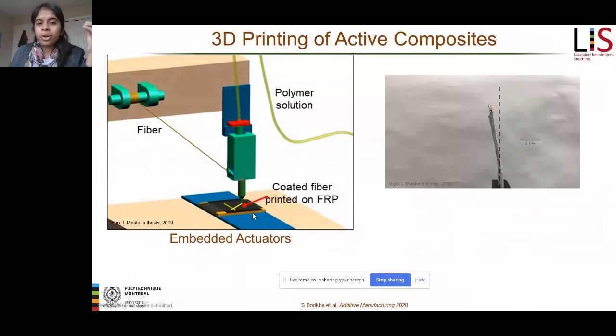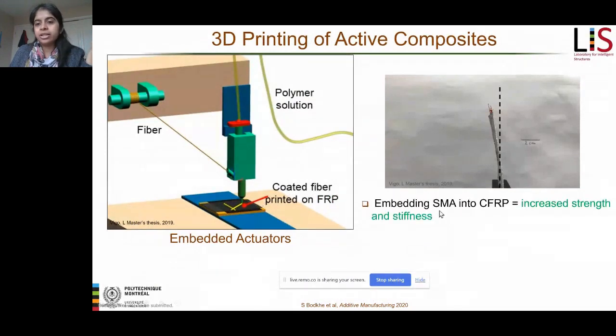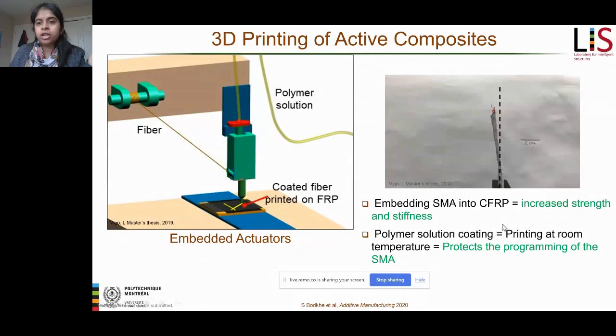So what we did was we tried to print these SMAs into composite prepregs. And then we cured these prepregs and we ended up getting really strong structures. So here you can see the video of the shape memory alloys, which are embedded into composite prepregs. And of course, we are still working on optimizing and making this even better at this point. But yes, as a proof of concept, this is a very good active composite that we have made.